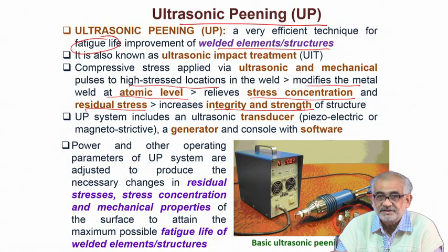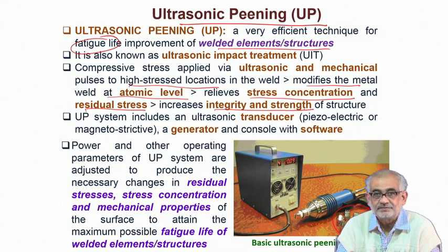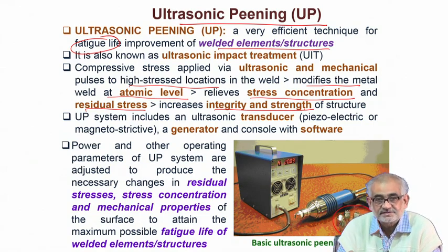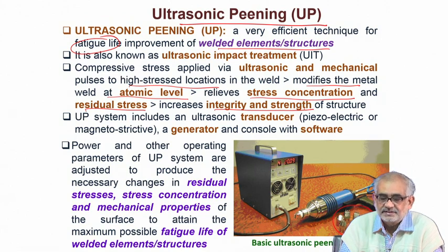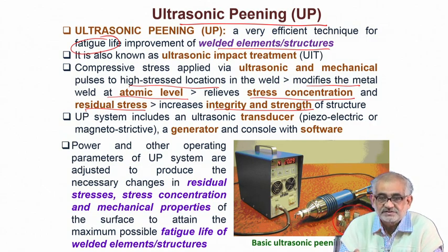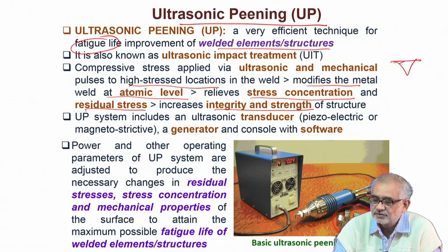Whenever we experience a solidification process, any liquid that solidifies tends to contract depending upon the coefficient of thermal expansion. When it contracts, the state of stress on the surface is tensile in nature. Any welded joint is therefore prone to cracking or failure because the state of stress on the surface is tensile. We would like to reverse that — instead of a positive (tensile) state of stress, we would like to create a state of stress which is compressive in nature. This is quite possible in a localized region using ultrasonic peening.